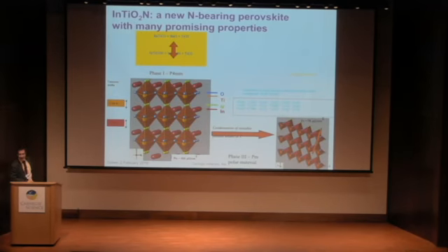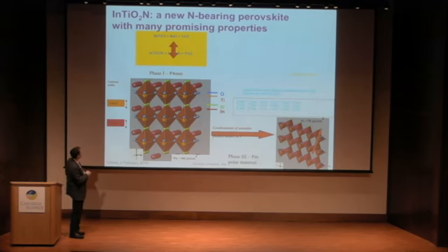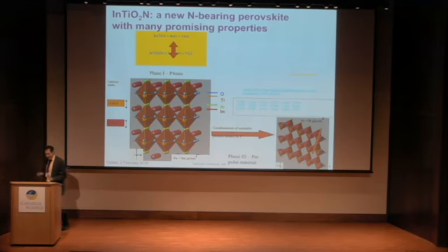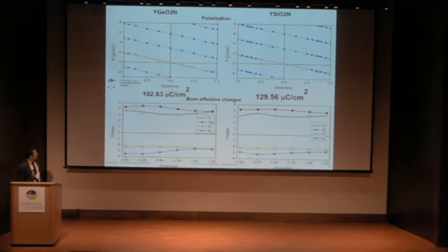Now, some things didn't work. They may still be interesting materials, but for example, here's kind of a counterexample. If you take indium titanium O2N and you start with something like this, it actually kind of falls apart and makes tetrahedrally coordinated ions. Looks nothing like a perovskite. It could be very interesting. I mean, we actually calculated the properties of this material, but it's not a perovskite, so we kind of didn't follow up on it any further. But there may be other interesting materials as well.